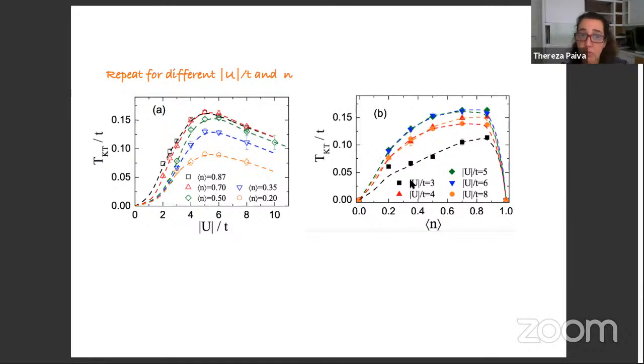So we do repeat this for a number of different U over T and a number of different densities, and we get these two plots. They actually have the same results, they are just plotted differently. So this is the Kosterlitz-Thouless transition as a function of U for different densities, and this is the same quantity as a function of n for different values of U. The first thing we realize by looking at this plot on the left is that the maximum lies at U over T equals 5 for all the densities we have analyzed. So this is the U that should be used in experiments, because this is the one that maximizes the temperature.